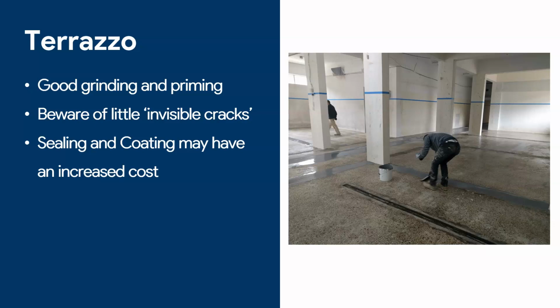Terrazzo, although a lot of it is cement or sand and that will stick, you also have these little particles in the floor that may not stick. So you always want to do a good grind over and scrape the surface, so whatever primer you use can penetrate the surface. You want to avoid just trying to paint over, because terrazzo, especially old terrazzo, has collected dirt over the years.